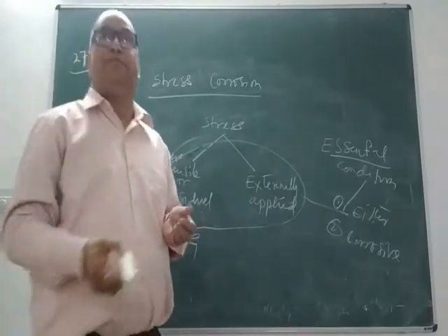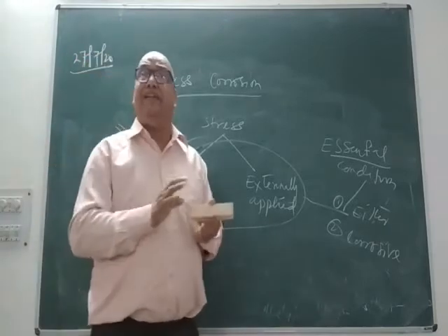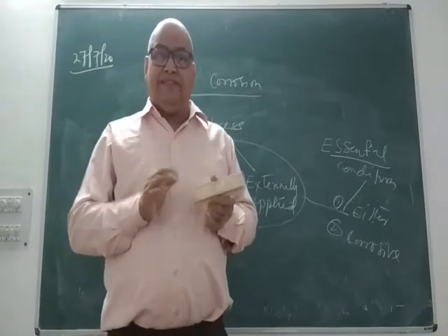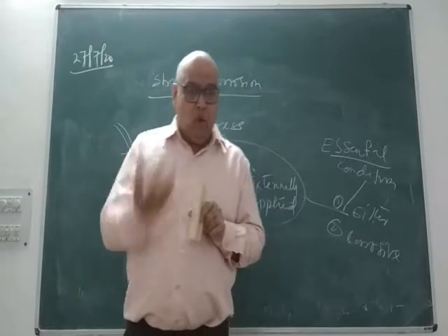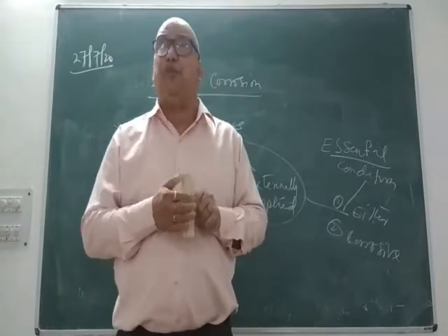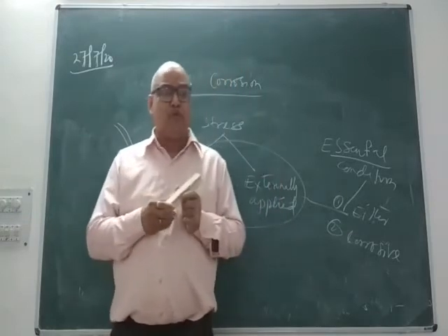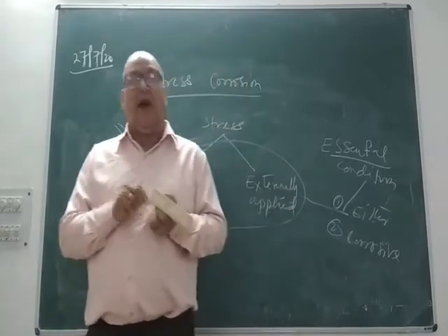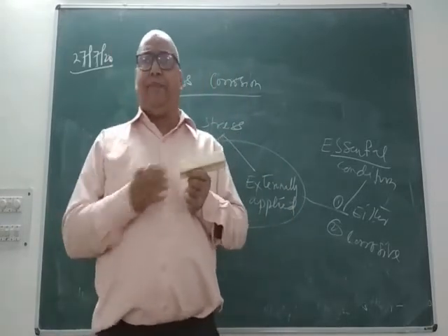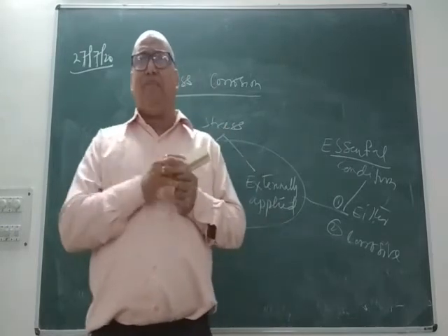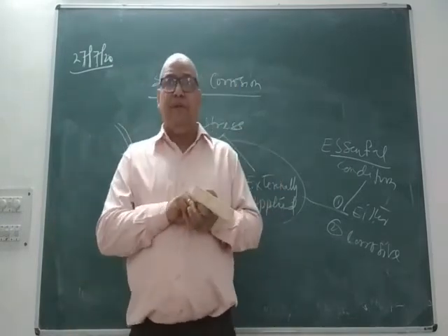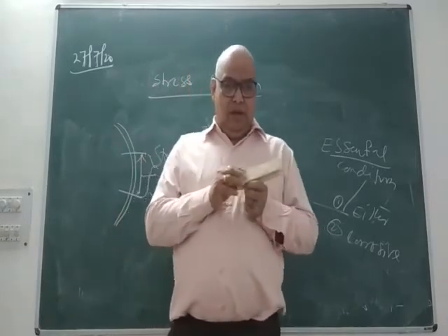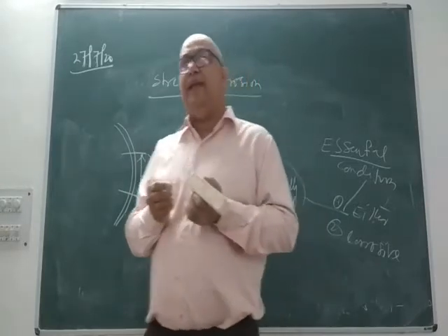Actually, this kind of stress corrosion is extremely dangerous because initially you will not get any kind of indication. Suddenly there will be a fracture causing a catastrophic failure. This type of corrosion is often found in fabricated articles of certain kinds of alloy like zinc brass or nickel brass, due to stress, and the stress is generated due to heavy working like rolling, drawing, and insufficient annealing.